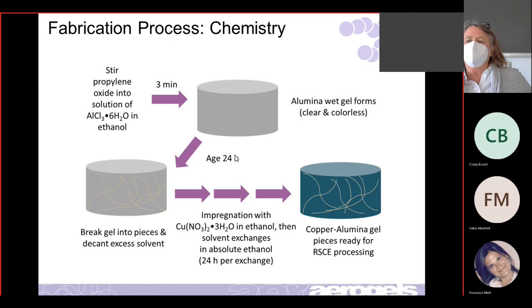Okay. And we have to do some solvent exchanges along the way. So this is not a fast process, not like the extraction is fast, but preparing the aerogels is not fast. You have to do these steps. But now I have a wet gel made of alumina with some copper in it.